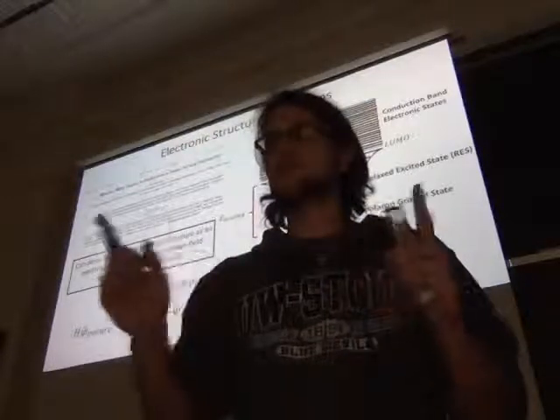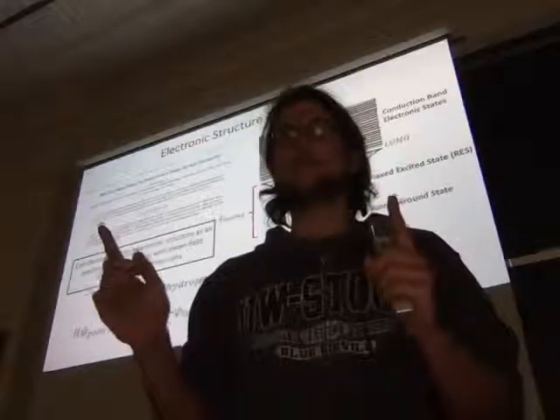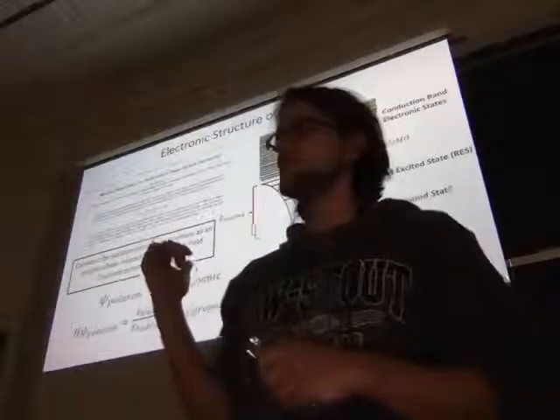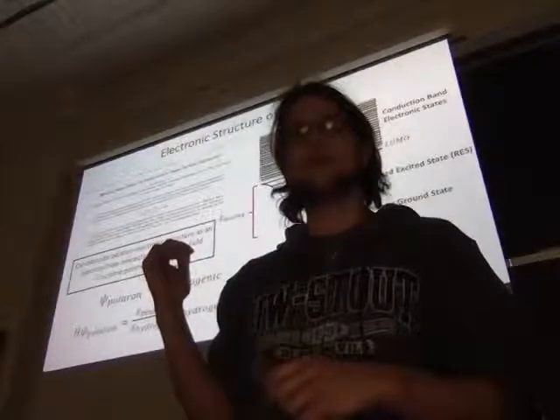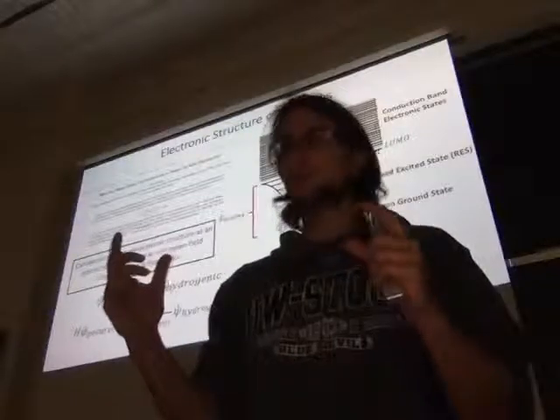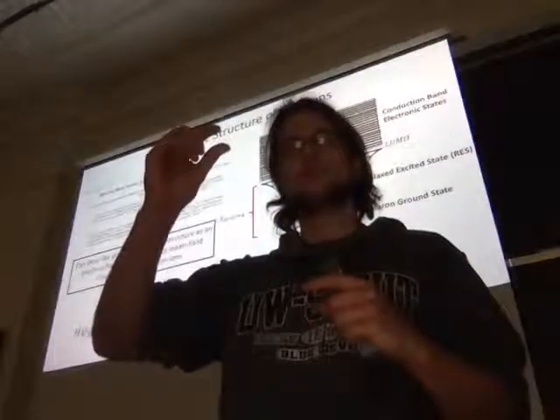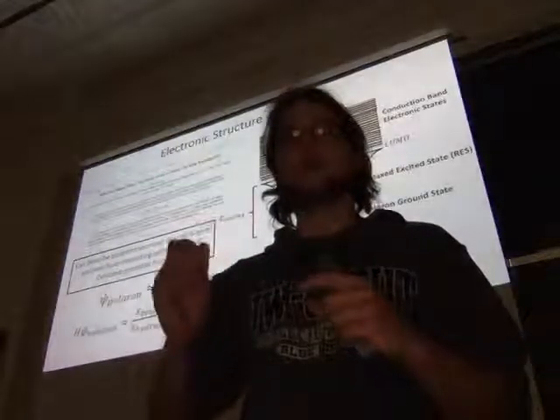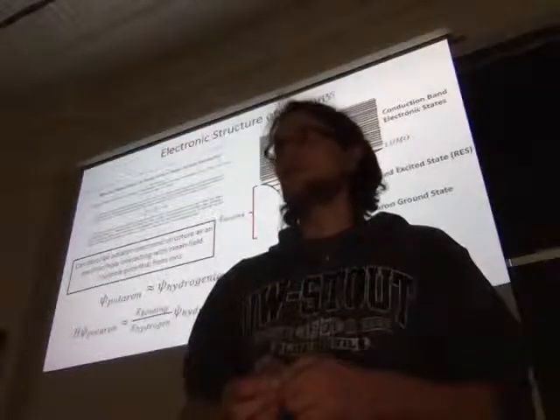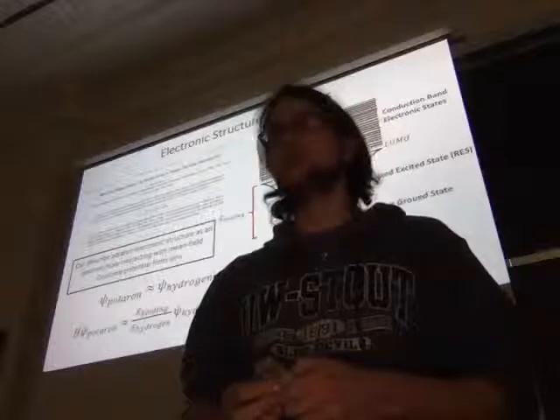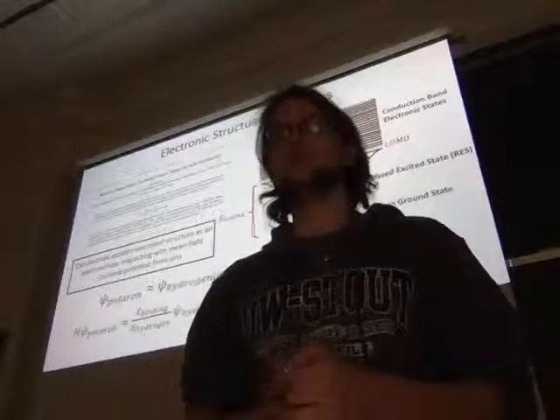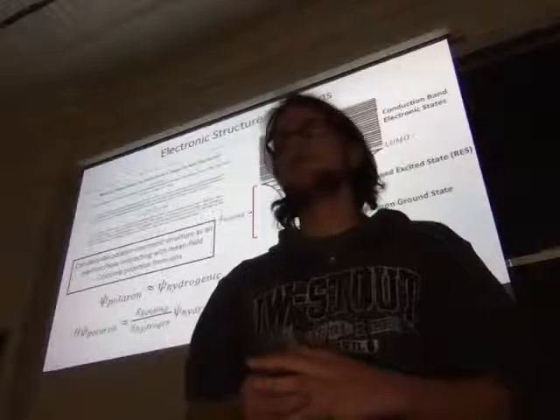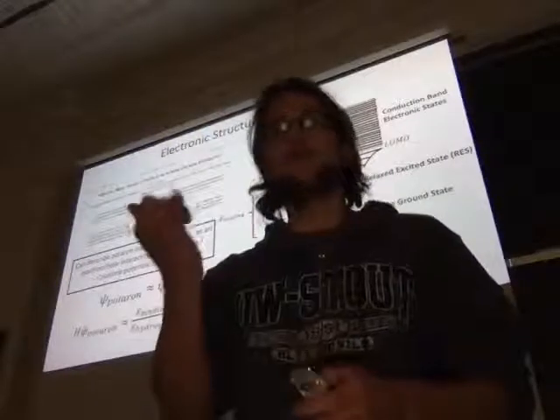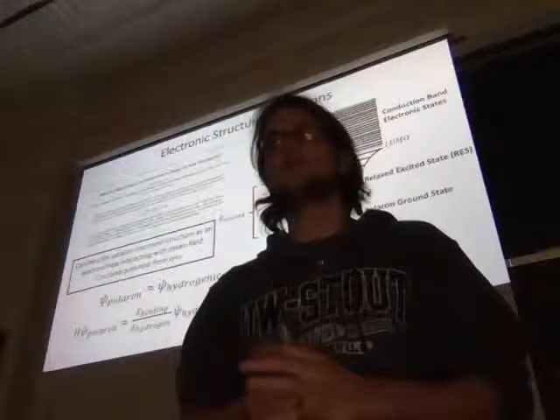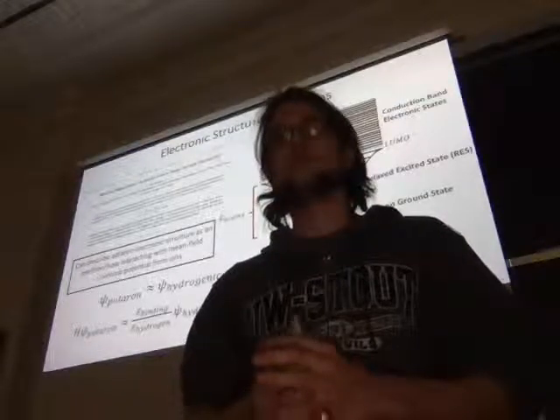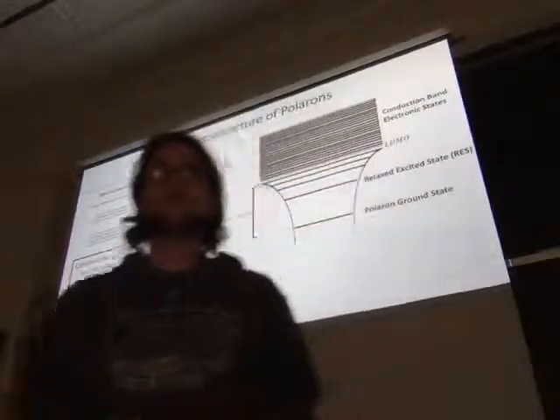Polarons can have a lot of different sizes, so there are different regimes. The ones in these materials, experimentally, are very large, like 9 nanometers. So it's not a very bound state, it's a shallower well. I'm not sure of the exact binding energies, but from initial computation it's around 1 eV binding. So it's stronger than a dopant impurity, but still less than the hydrogenic. It's an in-between, essentially.